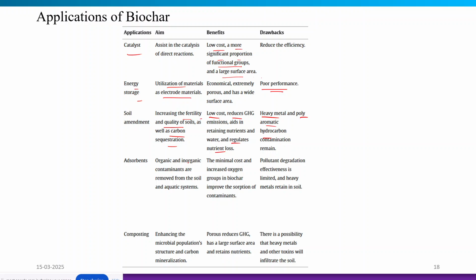In terms of the adsorbent, organic and inorganic contaminants can be removed very efficiently by different kinds of biochar adsorbent from soil as well as aquatic systems. It offers lower cost, and increased oxygen groups in the biochar improve the adsorption capacity for different contaminants. But sometimes the pollutant degradation effectiveness is limited and heavy metals may be retained in the soil for a longer time, which may create contamination. Also, if we compost the biochar, that will enhance the microbial population structure, which will ultimately enhance carbon mineralization. Thus they reduce greenhouse gas emission and also increase the nutrient value of the soil.